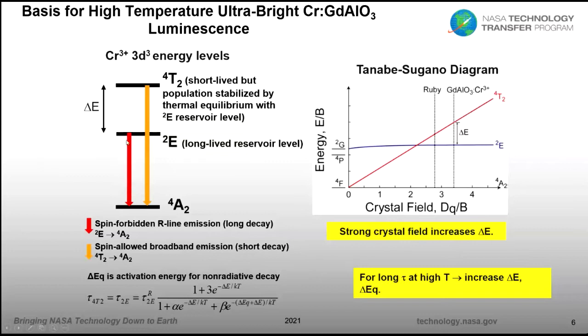In the approach we use, we take advantage of the fact that when a material becomes hot, you can start thermally populating the electrons that were already excited to this level up to the 4T2 level. And when that relaxes, you get a higher energy, shorter wavelength broadband emission. Typically, the 4T2 relaxation would be too short to be useful for temperature indication, but we take advantage of the fact that the 2E level below in this material acts as a long-lived reservoir. As you start depleting the 4T2 population, it gets replenished by this reservoir. The two relaxations come to thermal equilibrium, so they end up sharing the same decay time. You can look into the modeling of that and determine the decay time for both emissions. Tau is the decay time, and this shows its dependence on temperature.